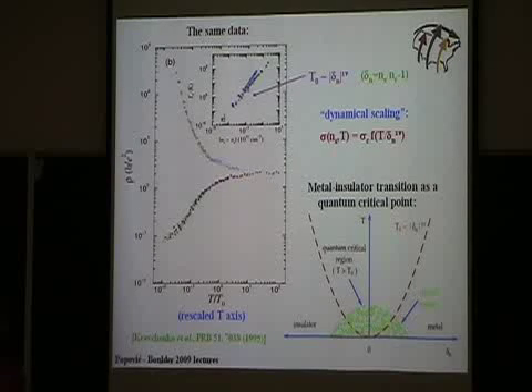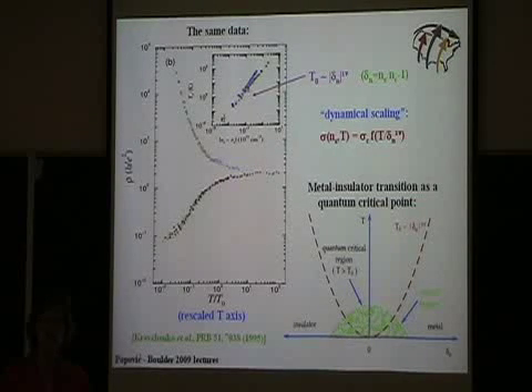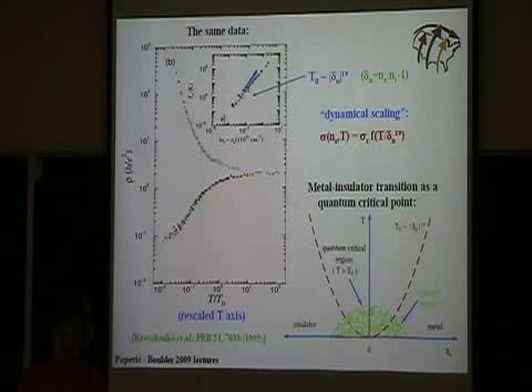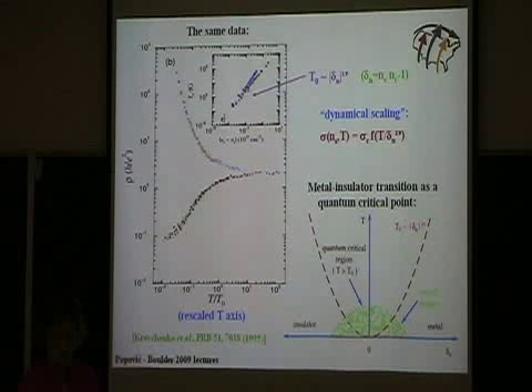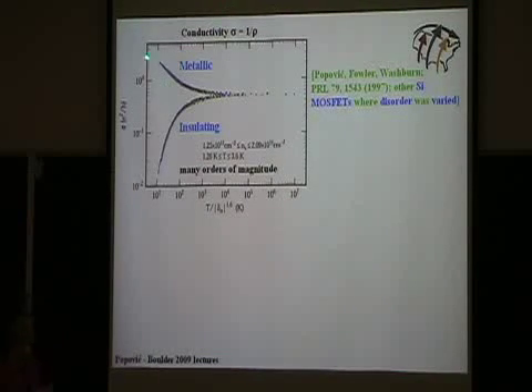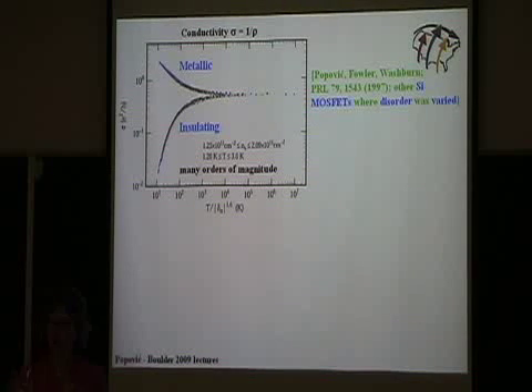And I had some samples where we could actually control the type of disorder. So for a certain type of disorder corresponding to this case, we found the scaling with the same exponent as Kravchenko. So these were totally different devices, and I think it was nice scaling. It was published in PRL 10 years after I actually took the data as a graduate student, so don't throw anything away.